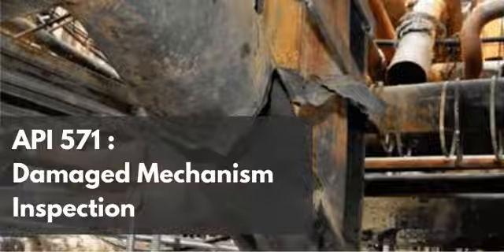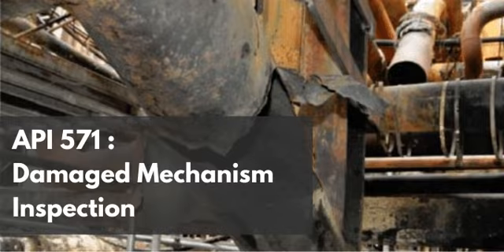The source data outlines 3 conditions that absolutely must be satisfied simultaneously for carburization to occur. It's basically the recipe for a metallurgical disaster. Let's hear them. Condition 1, exposure to a carburizing environment or carbonaceous material. Condition 2, a temperature high enough to allow diffusion. And condition 3, a susceptible material, which we just established covers almost everything with iron in it.